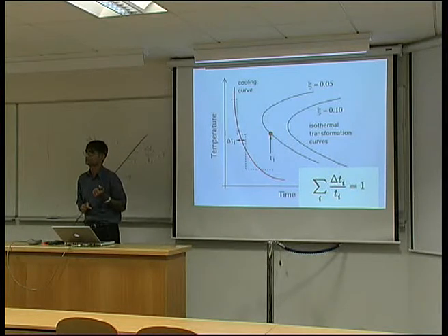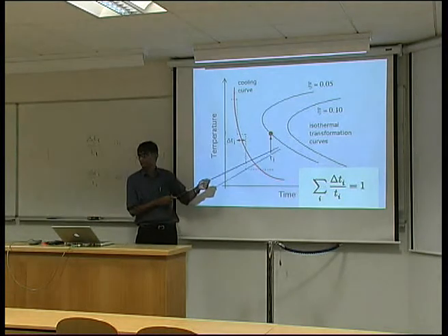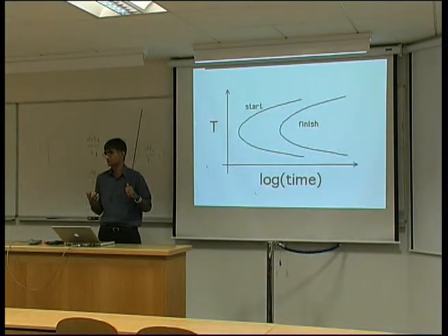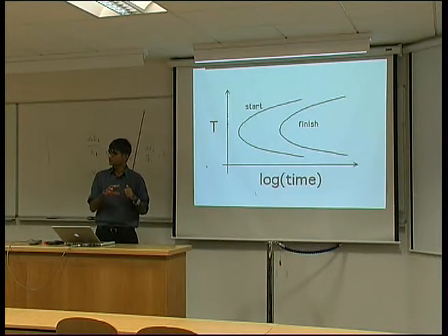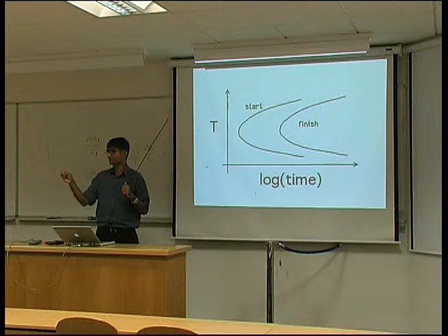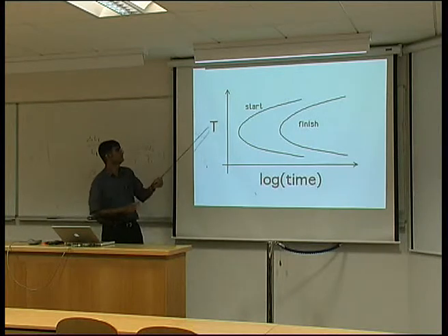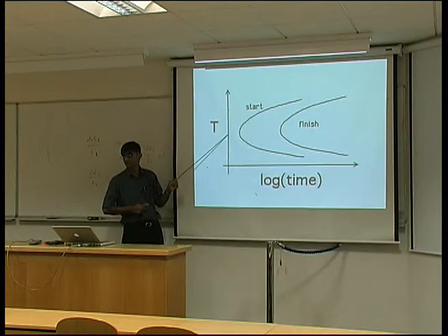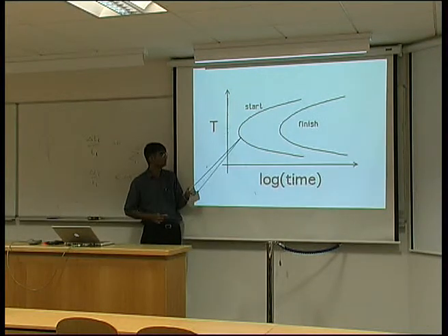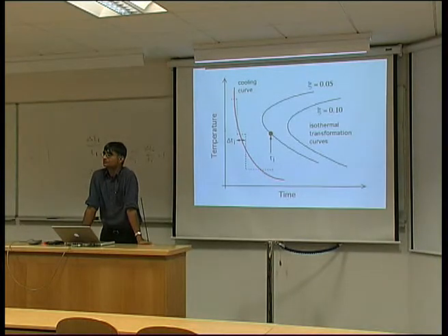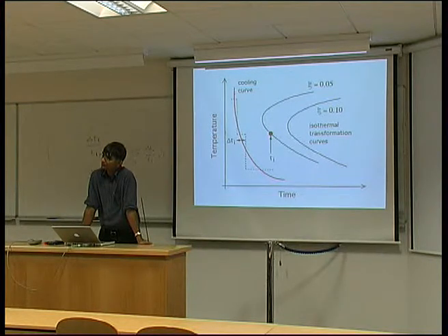What does it mean, isothermal? So this is what we've derived from our Avrami theory, or done in experimental measurement. So it's exactly the same as this diagram which was shown. There are two terminologies: one is isothermal transformation diagram, or time temperature transformation diagram. Isothermal is better because it tells you exactly that you're supercooling your parent phase to this temperature very rapidly, and then holding. And at this point, things start, and at this point, they finish. So obviously this means that one reaches the first curve somewhere in the curve. Doesn't matter where, because it's going to be some arbitrary time to reach that.